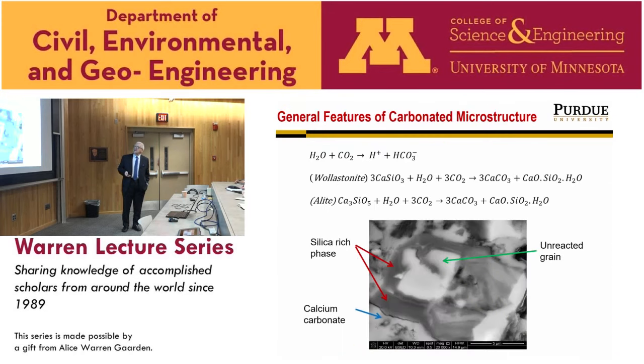If you look at a little bit more detailed scale, you will see that the silica gel actually forms a very tight layer around the unreacted grain. And there is also, this is the main binding phase, calcium carbonate. It turns out that the silica gel is not a pure silica gel. We call it calcium-modified silica gel. It actually has some calcium, and the amount of calcium that is present in the gel will actually determine the mechanical response and chemical response of the carbonated system. So we wanted to explore that to understand how we can either maximize or minimize the amount of calcium ions in the silica gel itself.